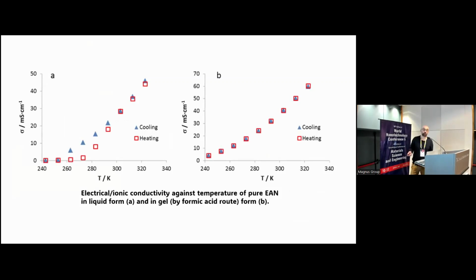On the left is the liquid, and on the right is the gel. You can see this difference between the cooling and the heating. This is because of hysteresis, quite typical of ionic liquids because of the supercooling effect, that the melting and the crystallization do not fall at the same temperature. And you can see that the gel has even a bit higher ionic conductivity than the liquid sample. This is quite a good result for us.